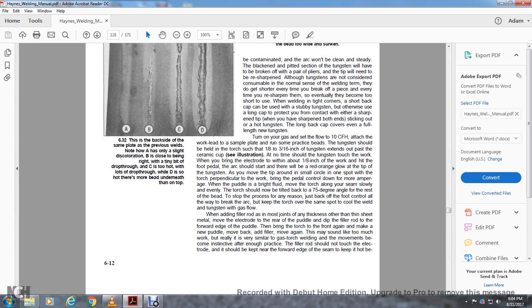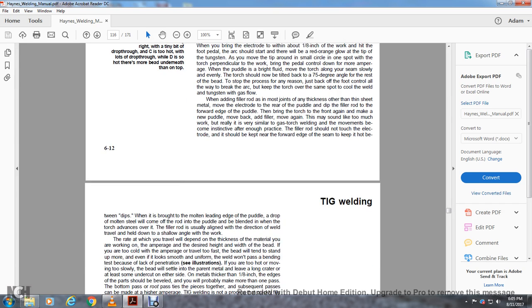When adding filler rod, as on most joints of any thickness other than thin sheet metal, move the electrode to the rear of the puddle, dip the filler rod into the forward edge of the puddle, bring the torch to the front again to make a new puddle, move back, add filler, move again. This may sound like too much work, but it is really very similar to gas torch welding, and the movements become instinctive after enough practice. The filler rod should not touch the electrode and should be kept near the forward edge of the seam to keep it protected between dips.